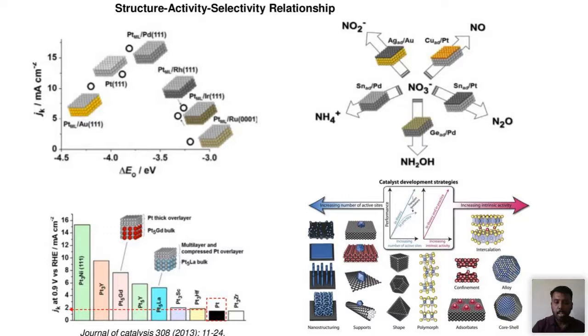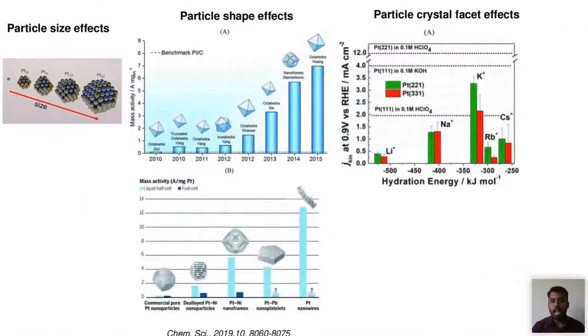Like platinum can be alloyed with yttrium, gadolinium, and also different lanthanide series metals you can use. They are inexpensive, and also you can use transition metals, and you can form an alloy to increase the activity. Different strategies have been used, like nanostructuring and support and shape and adsorbate and core shell or alloy structure. You can control the activity.